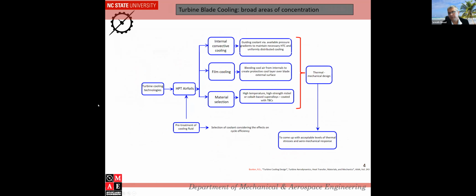So if you look at turbine cooling technologies, you have high pressure turbine airfoils, which is the first two stages of the airfoil of the turbine, which are the most exposed to the hottest conditions. You can actually pre-treat your cooling fluid, that is the air that I was talking about. Compressor can actually put an intercooler in there and reduce the cooling air temperature, but again, it adds bulk. So we are trying these kind of things in industrial gas turbines because they're not flying, but in aircraft engines, it's not going to be possible.